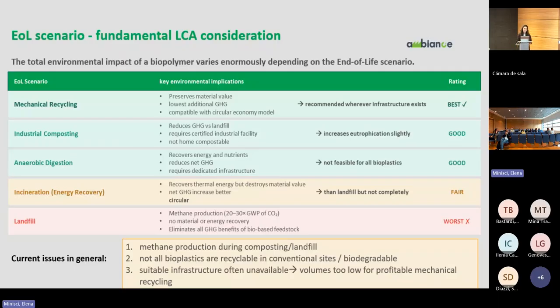And then there is the last one, that is the landfill. That is the worst one because when you leave these materials in a special site, they produce methane that has a global warming potential 20 times higher than CO2. So you eliminate the benefits that you gain with this material during the carbon uptake.